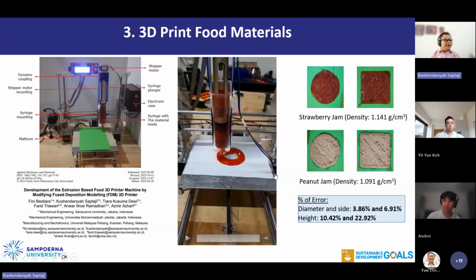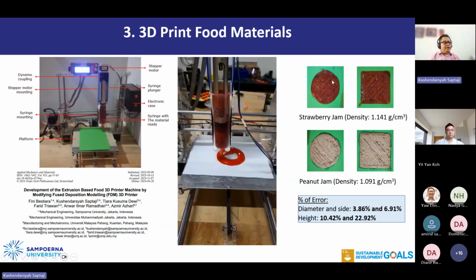Okay, so after modifying the machine, we measure the dimensions of the printed jam compared with the design. Basically, there's still some error: the diameter and side error is about 3.86% and 6.91%, for the circular shape and the rectangular shape respectively. There's also an error in the height, which is quite high, so we still need to improve this. However, this result has been published in a conference about 2 years back.